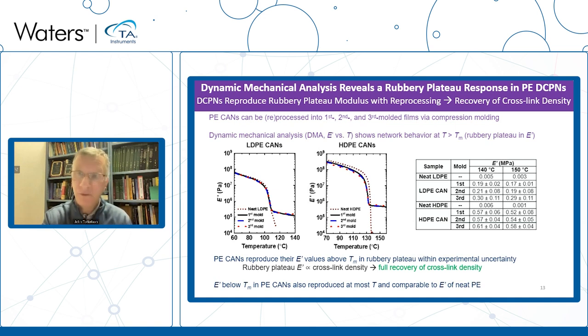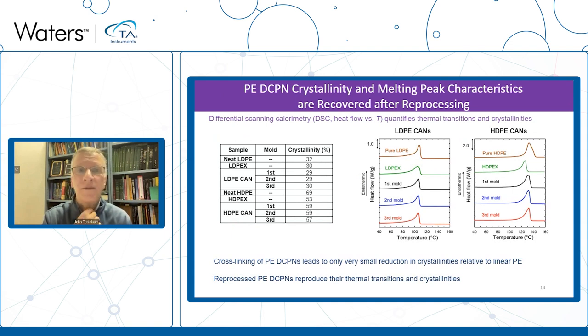These particular results are actually for virgin polyethylene materials, but we have also done work using waste materials, actually obtaining plastic grocery bags from a grocery store. That's low-density polyethylene. And going to a grocery store and buying a gallon of milk, and the milk jug is high-density polyethylene, and we obtain very similar results for the waste materials in those particular cases as well. And so this is a circumstance where this can work with virgin or with waste materials in terms of upcycling these particular thermoplastic materials into higher value network materials. But these networks can actually be reprocessed multiple times. We also illustrate here that the crystallinity levels and the melting peak characteristics are also highly reproducible as a function of molding cycle in these particular cases.